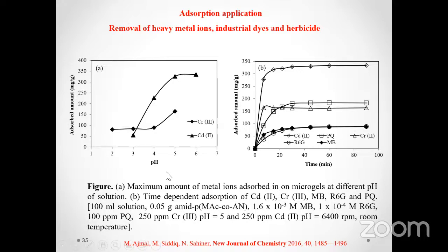And in this respect, the hydrogels are being considered as very interesting materials which can be used as adsorbents for the treatment of contaminated water. For example, in this study, which I am going to present here, we have used this hydrogel system for the adsorption of 3 different types of pollutants. These are the heavy metal ions and the dyes. Among the heavy metal ions, we have studied chromium and cadmium. Among the dyes, we have studied rhodamine 6G and methylene blue, and a pesticide, which is paraquat. And it was observed that this system can adsorb all these types of pollutants from the contaminated water.